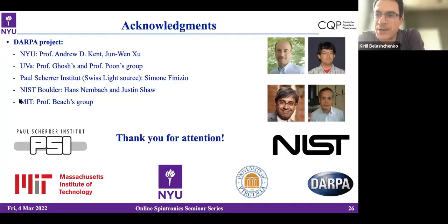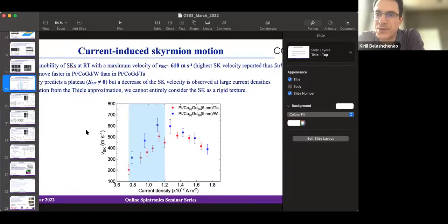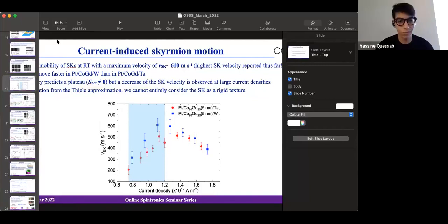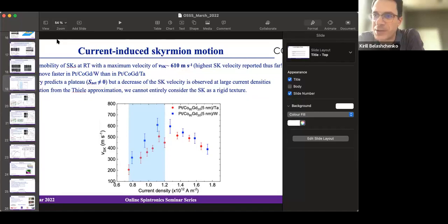Kirill, please go ahead with the question. Yes. Thanks for the interesting talk. I have a simple question. So you showed the plot of the Skyrmion velocity as a function of the current density that saturated. And you said it's because of the Joule heating that moves you away from the compensation point. So if you took a different concentration so that the compensation point was higher than room temperature, so that you would actually approach compensation with higher current density, would you expect like a super linear growth and potentially higher Skyrmion velocity?